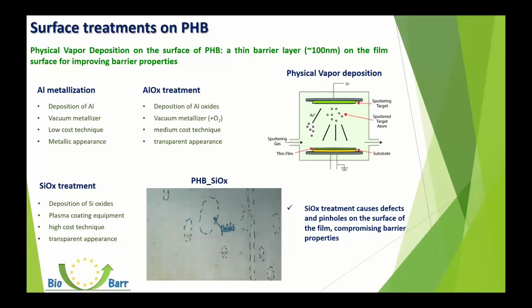Also, as discussed in the previous presentation, by surface treatment we refer to treatment in which, by physical vapor deposition, a thin barrier layer is applied on the surface of a film for improving barrier properties. This is a common method used in flexible packaging to improve the barrier properties of the films. And the main technique used is the conventional aluminum metallization. Also, the AlOx treatment is used, and it's starting to become more used.